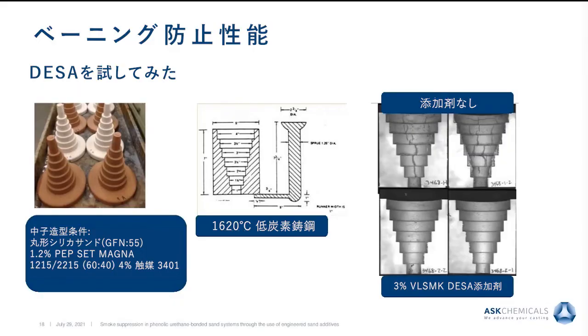So what's the next feature that the sand additive needs to have to be a good sand additive, right? Well, the anti-veining functionality needs to be there. So for that, we need to go back to the foundry and lab and do some testing. So we took some of our step cones that we made earlier, but this time we placed them in PEP SET molds and just did a normal pour. And the result of these castings is now shown on the right side. We cut the step cone casting in half, so you can see the inside of the step cone.